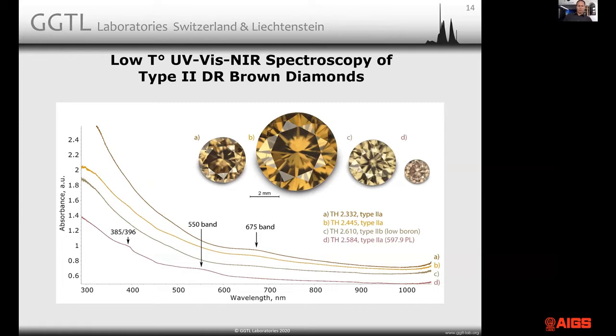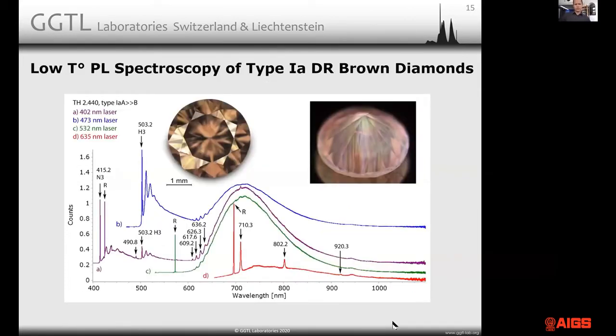The pinkish one, sample D, is kind of exceptional because that's a stone that shows photoluminescence that has been assigned to oxygen. They have created that by oxygen implantation in natural diamond, and this is what we found in natural untreated diamonds. So these are the relatively unspectacular low temperature spectra of type 2 diamonds. Going to photoluminescence from here.